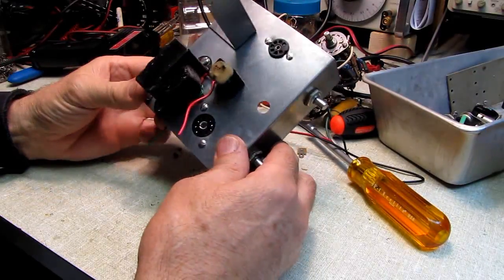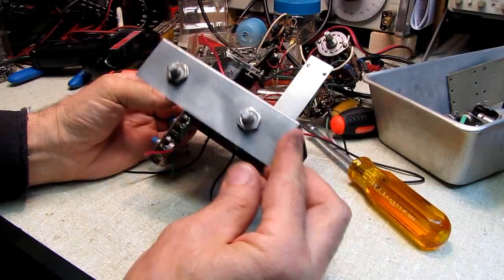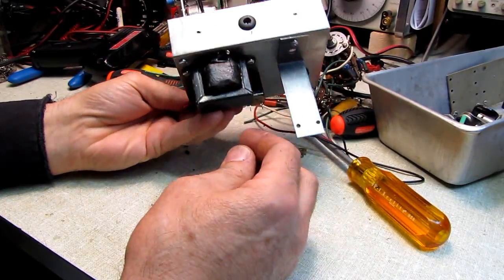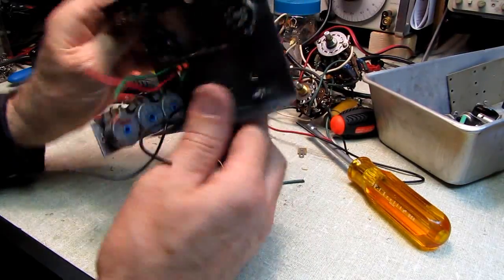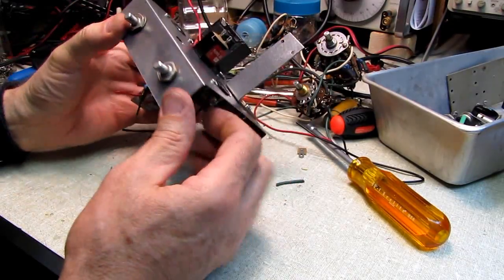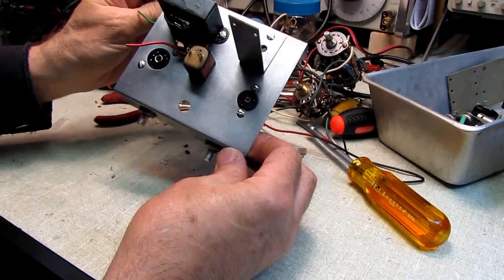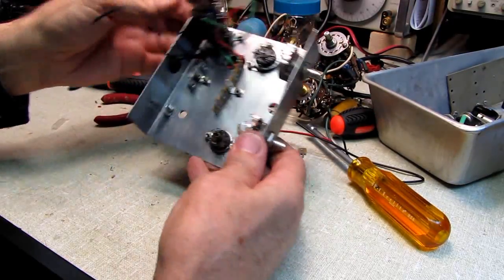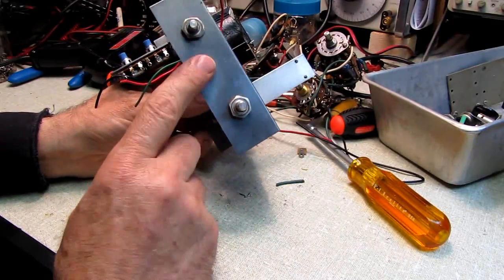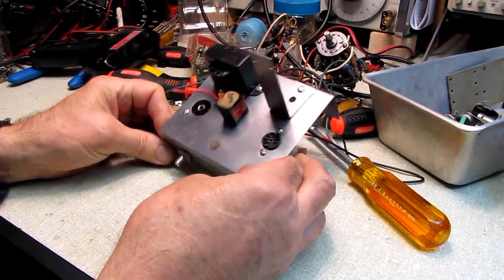We've begun the rebuild of the Eico chassis. The plating, I think, came out looking fantastic. This almost looks like a new unit now. We've sprayed a little paint on the power transformer. Our new tube sockets are in. I've put some new wires on the transformer. This was done with four 15-minute cycles in the bath for the plating.